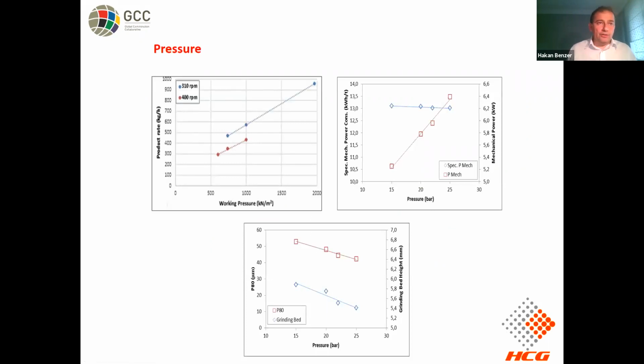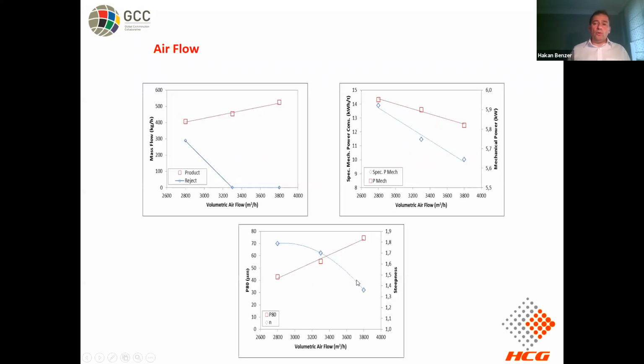Again, the other effective parameter is the pressure. So once you increase the pressure, the production rate increases because you are producing more fines. Inevitably, as soon as you produce fines, the air suction takes the fines out from the system. If you increase the pressure, of course, the production rate increases, pretty much in the normal range, specific energy consumption stays constant, while of course, the mechanical power is increasing. With the pressure value, of course, the product gets finer and the grinding bed height reduces. These are all important for us to evaluate in our modeling studies.